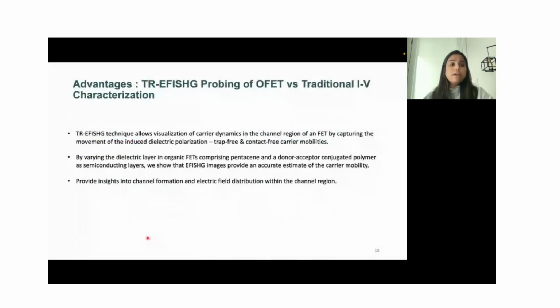Thus, in summary, there are several advantages of the TR-EFISH probing of the OFET versus the traditional IV characterization that I have mentioned here today, where number one is the direct visualization of the carrier dynamics in the channel region of these transistors, which enables us to calculate trap-free and contact-free transport parameters. Moreover, by altering the interfaces of the semiconductor dielectric, we can get a direct insight into the effect of the interface on such transport parameters, as well as direct visualization of the channel formation and electric field distribution in the channel region. This also enables us to understand the performance of such semiconductors, and thus helps us to tap into the full potential of such systems when used in this technology.